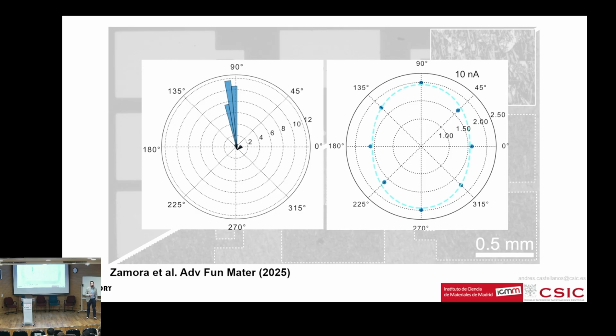And in principle, you could use the same concept to form a twisted bilayer, more or less with a controlled angle. Yes, but the problem is our flakes are typically tens of nanometers thick. So one transfer is typically 10 to 40 nanometers thick, something like that. So then you can transfer two films with a controlled angle between them. Yes, we have done that, but it's not going to help for magic-angle twisted graphene, for example, because we don't produce single layers with this method. Yes, but the stacking between the two last layers will be controlled. Okay. So you will have the moire just at the interface, because the rest is going to be relatively thick.